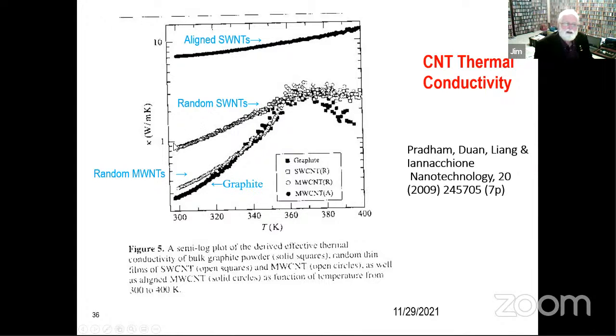We can get better by an order of magnitude at 300 K with single wall nanotubes rather than multi-wall. But if you're going to line those single wall nanotubes up, well, we're going at least 1.5 orders of magnitude. So this is a possible solution to the thermal problems in packaging.